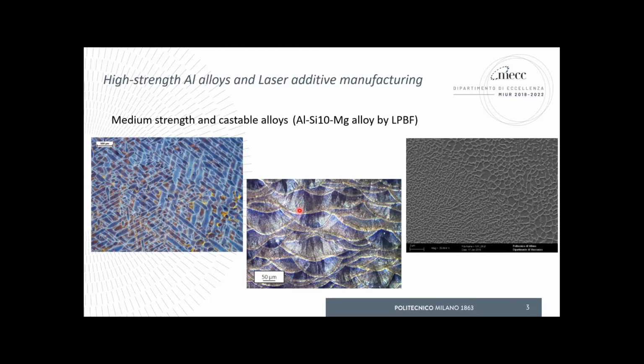If we do a lateral cross-section, we see very distinctively the melt pools, and we notice the columnar grains that are growing according to the thermal gradient. And if we increase the magnification even more, we can see a very nice, very fine cellular structure, which can be found inside those columnar grains. For this kind of alloys, everything goes very smoothly during processing. Usually, you don't have any specific trouble with defects, provided the parameters are set according to the best option.